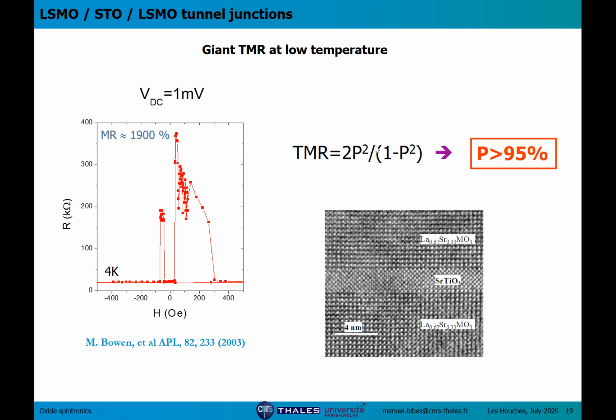So from this value of the TMR, you can use Julliere's formula and extract the value of the spin polarization, which here is more than 95%. I must say that this is at 4 Kelvin. And at room temperature, I will show you, unfortunately, the TMR of the LSMO junction is vanishing.